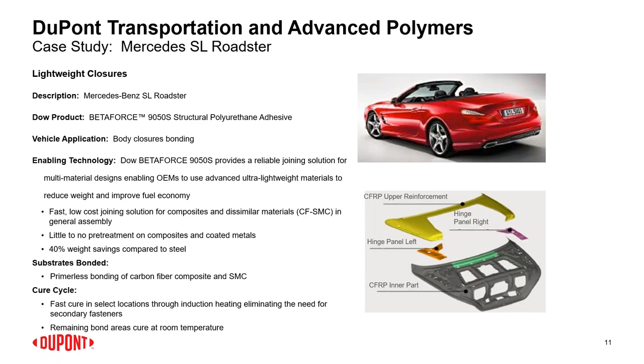So just a few examples to highlight, you know, the Mercedes SL Roadster, the closure, the trunk lid, right? We use our Betaforce 9050S, which is a fast curing, high modulus adhesive, to bond the carbon fiber inner and outer parts. This was some ultralight materials that helped really reduce weight by 40% compared to the steel structure. And this was all bonding with carbon fiber and SMC.